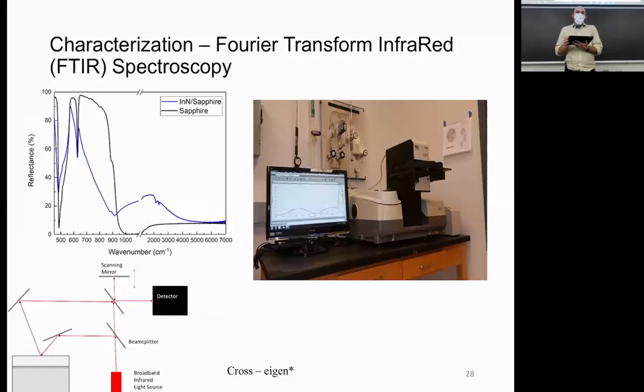We did FTIR, Fourier transform infrared spectroscopy, which gives us those same wavelength related features that happen at higher energies, but they also give us the features that are related to the crystal structure. So these features that you see down here are related more to the way that the material actually absorbs light due to the spacing in the crystal.